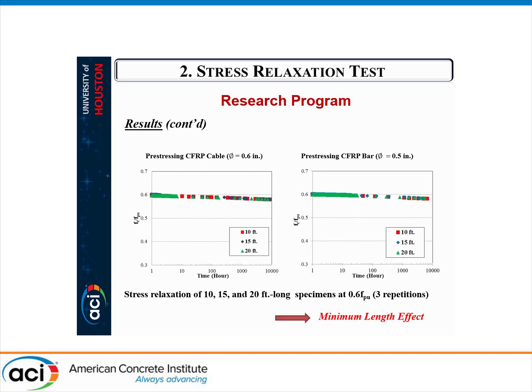Also, here we have the result of the specimens with different length, but at the same level of prestressing of 60%. And as you can see, for 10 feet, 15, and 20 feet, the results are on top of each other. So we concluded that the length has no effect on the relaxation, or has a minimum effect.